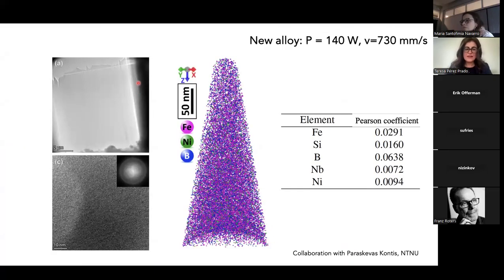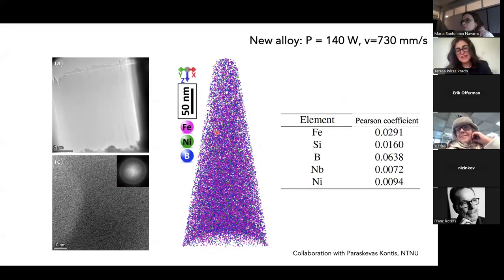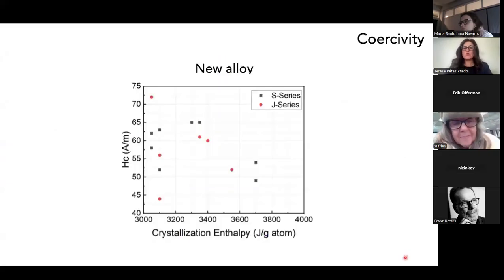We also did some TEM of a FIB-milled lamella, which was, again, fully amorphous. And we went even to the atomic scale to see the mixing of the different elements. The Pearson coefficient is very low, so this makes for an almost fully random mixing of the elements. This was a collaboration with Professor Paraskevas Kontis at NTNU. So it looks like over a very wide processability window, we now have relatively high density with quite high amorphous fractions.